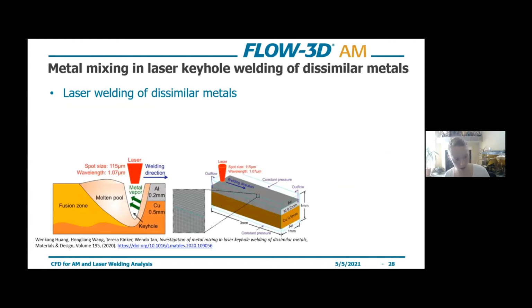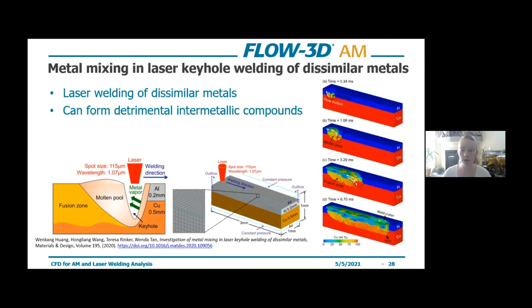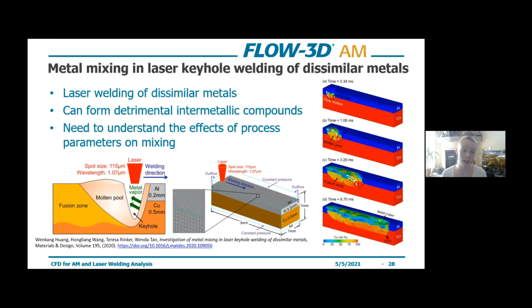So in this study from researchers over at GM, they looked at laser welding aluminum and copper in a lap joint configuration. And what's important here is that you get sufficient mixing so that there's sufficient fusion between the 2 alloys, but too much mixing can result in detrimental intermetallic compounds. So finding that sweet spot, finding the threshold, and identifying the process parameters that are going to lead to that place where we have sufficient fusion, avoiding the intermetallic compounds. We need to understand the effects of these processing parameters on the mixing, and modeling is a super convenient way to qualify that and look at the quality of the mixing at a very detailed level.